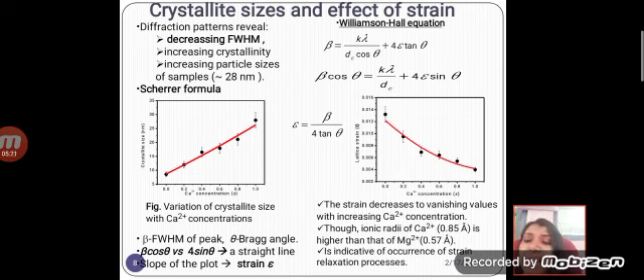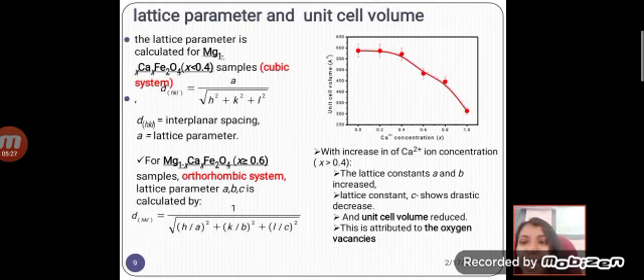So we can see that the strain decreases to vanishing values with increasing calcium concentration, and this is related to the ionic radii of the magnesium and calcium samples. And the lattice parameter and the unit cell volume were calculated. The interplanar spacing d_hkl is a by root of h square plus k square plus l square, and from that we have calculated the lattice parameter and also the unit cell volume.